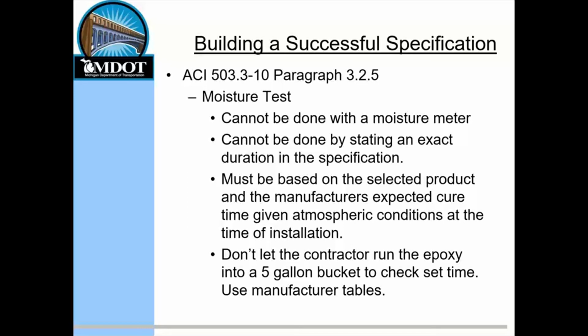And another thing is to make sure that the contractor doesn't just dump a bunch of epoxy into a 5-gallon bucket and see how long it takes to set. Epoxy is a very exothermic reaction. That set time won't match the set time that is going to be on your deck. The contractors have to follow the manufacturer's guidelines for set time and temperature.